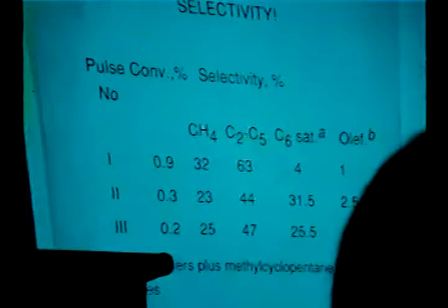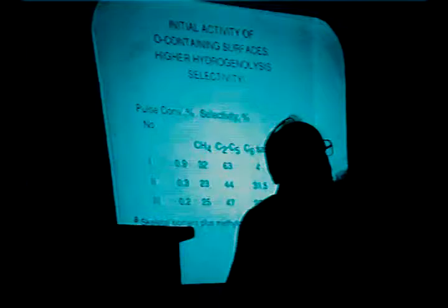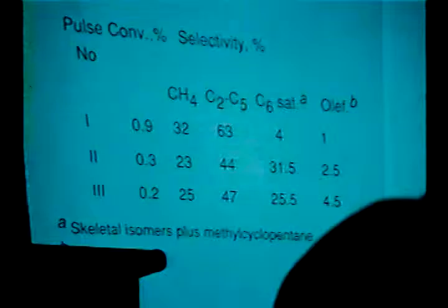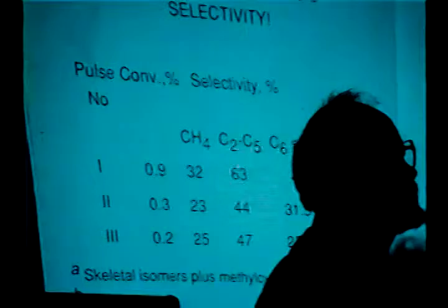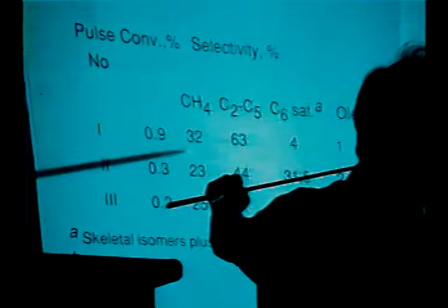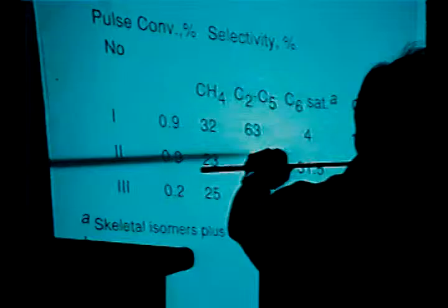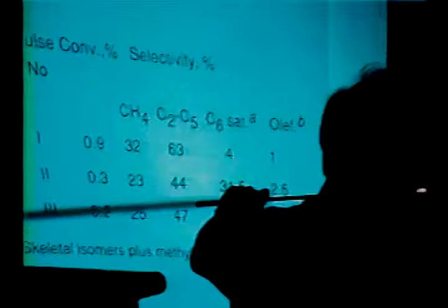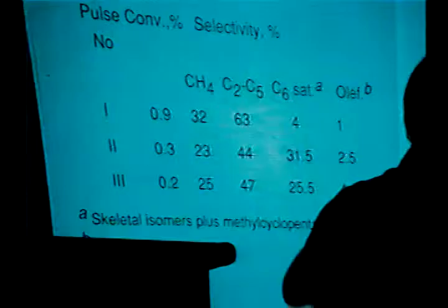Just a short comment on the catalytic consequences. It has been frequently reported in the literature that the oxygen-containing, oxygen-pretreated surfaces have higher hydrogenolysis selectivity. For example, Gao and Schmidt reported it recently for ethane hydrogenolysis in general catalysis. And we did some experiments separate to surface investigation, where we were introducing pulses into an oxygen-treated catalyst, into hydrogen carrier gas, and indeed a high hydrogenolysis selectivity was found in the first pulses, and in the later pulses the non-degradative product appeared in rather marked selectivity.